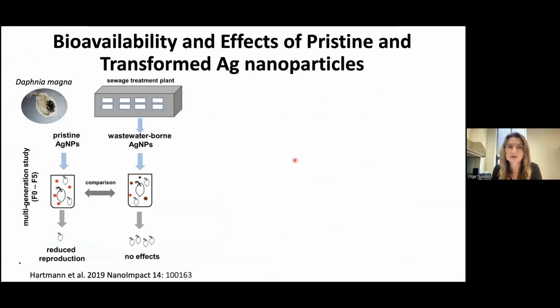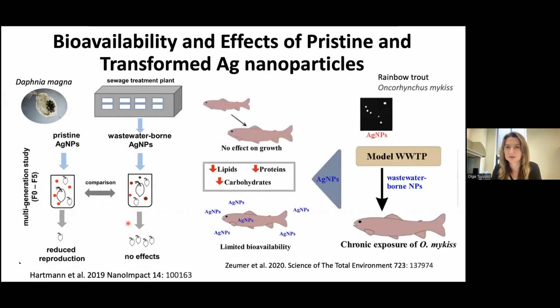So now just a couple of examples. For example, if we look at pristine versus transformed silver nanoparticles. In this study, the silver nanoparticles were called wastewater-borne silver nanoparticles. Basically, pristine silver nanoparticles were introduced through a pilot sewage treatment plant, and then that wastewater was used for exposure of daphnids. If we compare pristine versus wastewater-borne silver nanoparticles, there is definitely reduced reproduction over multiple generations in response to pristine. However, we don't see those effects in response to the transformed ones. And those are likely just sulfidized silver nanoparticles.